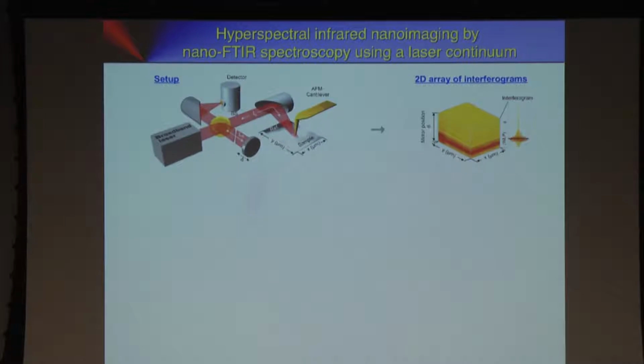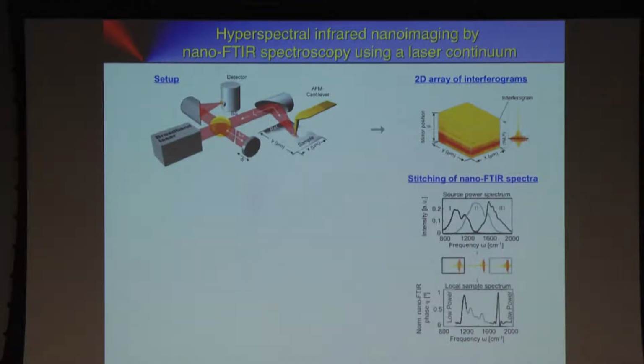So this is a setup the same as we showed before. Now the only thing we did is we scanned, instead of taking a point spectrum, we took a spectrum at each pixel, or more precisely, in an array of about 100 by 100 pixels, we take interferograms. Each interferogram is Fourier transformed, and then we get a hyperspectral data cube. The problem is we have a bandwidth limited laser. If you want to have a broadband spectrum, we need to detune the laser. So we did the following. We took these data cubes three times at different laser settings, so at 1, 2, and 3, and so we have this overlapping spectral coverage. So we take data cube 1, data cube 2, data cube 3. Then we Fourier transform them, and then we stitch these three cubes together. That is, of course, connected with a lot of challenges. We need a very stable laser, very stable scanning, and so on.